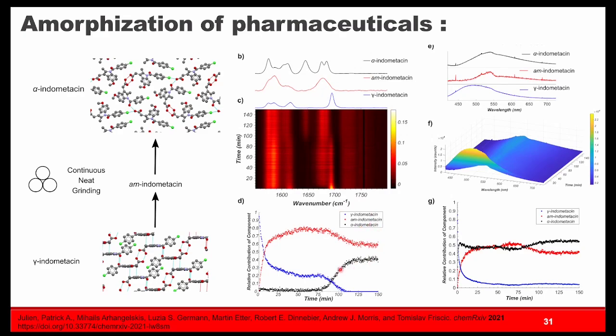So this amorphous phase, which is formed by the mechanochemical means in the reaction, relaxes so fast that you can't really characterize it by looking at the end point of the reaction. So this really shows where in situ techniques can be really powerful in terms of understanding the mechanisms of what's happening and looking at things like, are there amorphous phases involved in these types of transformations? And how are they interacting with materials while they're being ground in the ball mill?